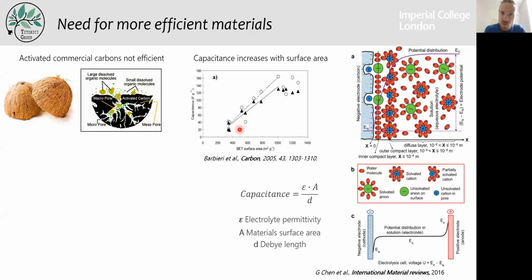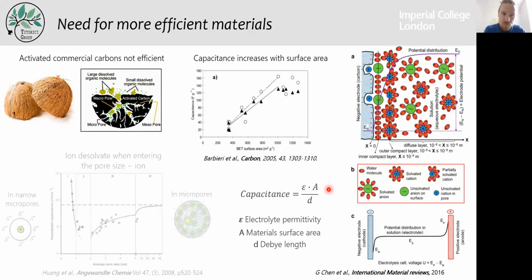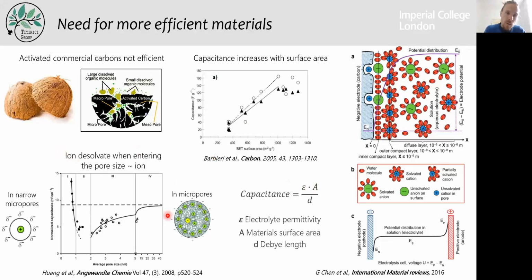For a long time, we thought that capacitance was only proportional to the surface area of your carbon. So people were trying to develop the surface area, as capacitance is proportional to it. But then we realized approximately 15 years ago that there is a massive dependence between capacitance and pore size. When you decrease the pore size, going from a macropore to micropores, and when the pore size starts to be the same as the ion size, then you start observing a massive increase in capacitance.